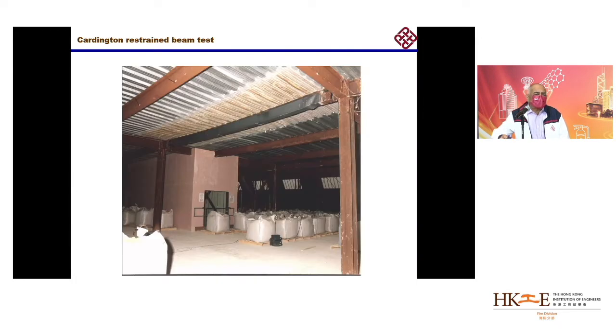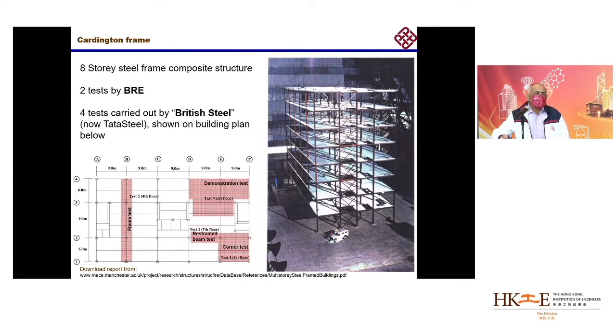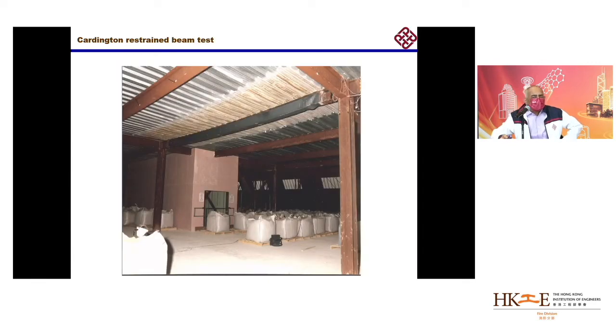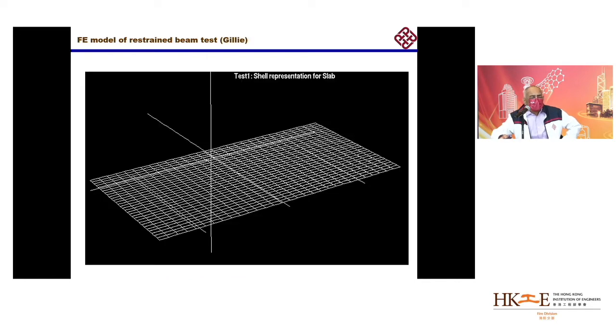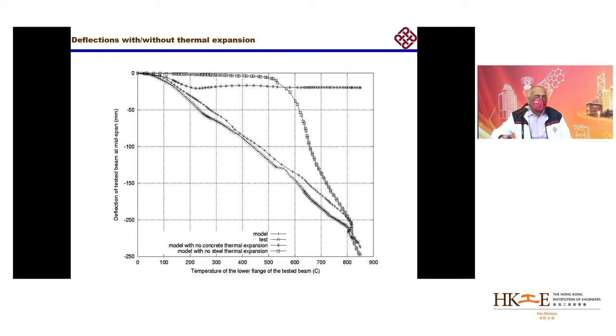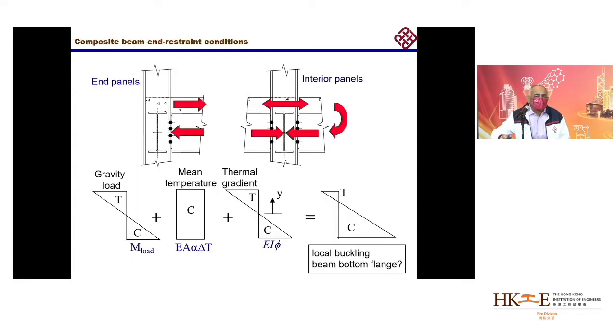And this is then seen in real structures. This is the Cardington test that we were involved in the mid-90s in modeling through a research grant. This is one of the tests of a beam. You can see the discolored area; that's where the fire was. We made a model and looked at the results. The model shows that the deflection and the bottom flange temperature is just a straight line, but if you change the thermal expansion coefficients of steel and concrete, then you get completely different figures. I won't go through that because it gets a bit complicated.